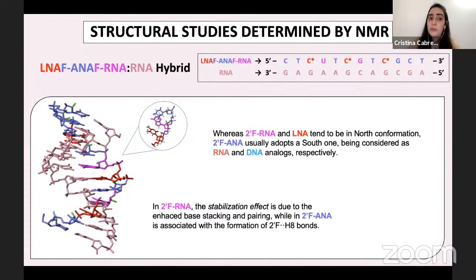In the first structure, a thermal enhancement has been seen, whereas FRNA and LNA show a north conformation. The stabilization related to base pairing in FANA is due to the formation of bonds between the fluorine atom and the H proton of the purine, adopting a south conformation.